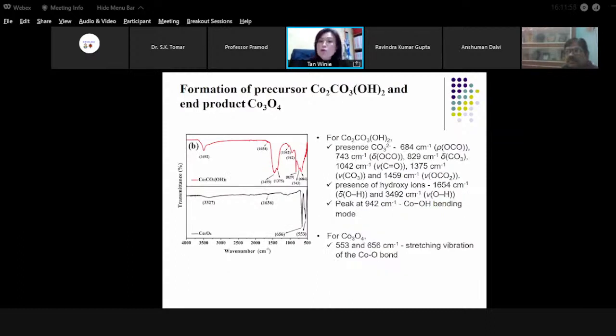Okay, we do the same for the structural properties using the FTIR for both the precursor, the cobalt hydroxide carbonate, and also the cobalt oxide. The presence of these are the characteristics for the precursor, and the composition of the cobalt oxide is indicated by the presence of peaks at 553 and also 656. These two peaks correspond to the stretching vibration of the cobalt oxygen bond.